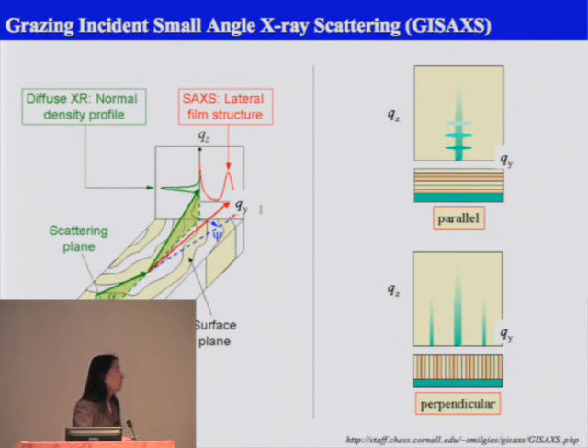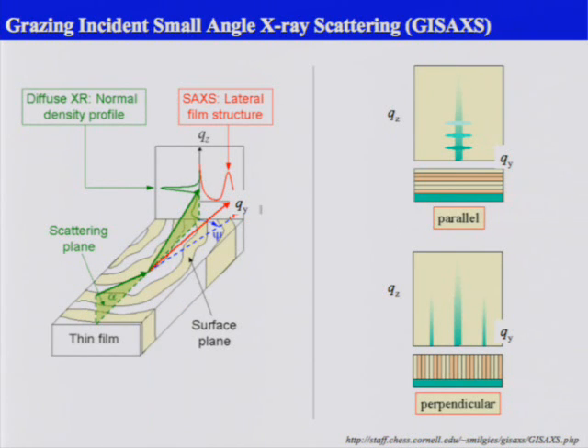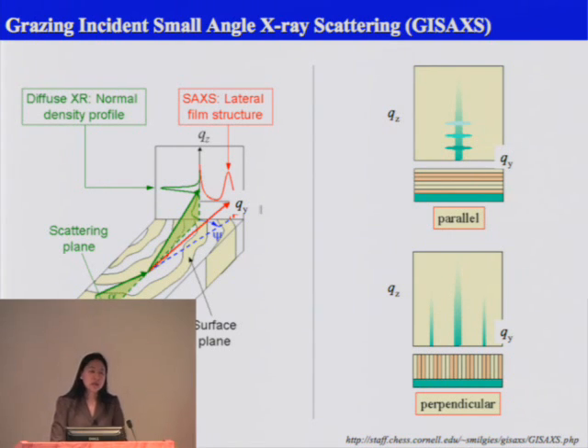What is it? In this case, this is my substrate, and I'm bringing an X-ray beam at a very shallow angle. If I shine an X-ray beam onto the surface at a very shallow angle, the X-ray is going to bounce off the surface and carry the information of the ordering inside the film. You can imagine the beam has a certain width, in this case about 20 to 50 micrometers.